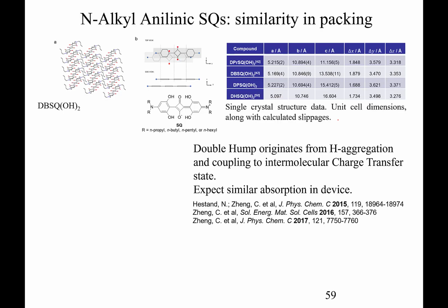It turns out if we look at a whole bunch of different anilinic Squaraines, anilinic Squaraine is this benzene ring in here with the nitrogen group on the side. And from that nitrogen group, we have these R groups. So if we increase the R group from 3 carbons in here, so this is a propyl, this is the butyl, this is a pentyl, and this is the hexyl. So as we do this, what this table signifies is that there's no real change in the crystal